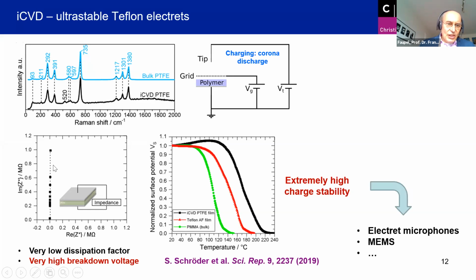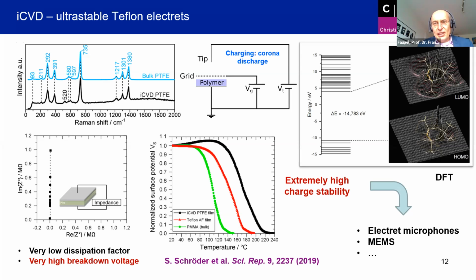And so here's a typical example of such a Teflon film. And to make electrets, we charge those films up in a corona discharge and incorporate permanent charges. Electrets are very important in MEMS technology, in electret microphones and many other fields. And our thin film electrets, which are particularly interesting for MEMS, they have a much higher charge stability compared to commercial films shown here. I will not go into details. We develop such electrets not only by trial and error. Recently, Stefan Schröder from our group, who runs the electret group, also carries out density functional calculations to get information on the trap depths of the materials and to tailor them through theoretical design.